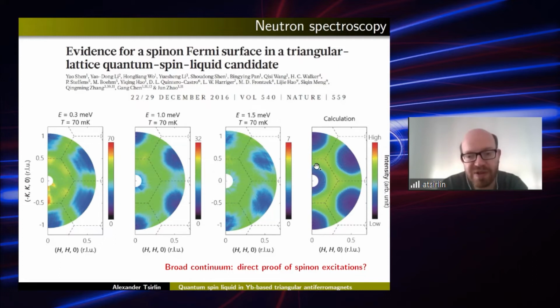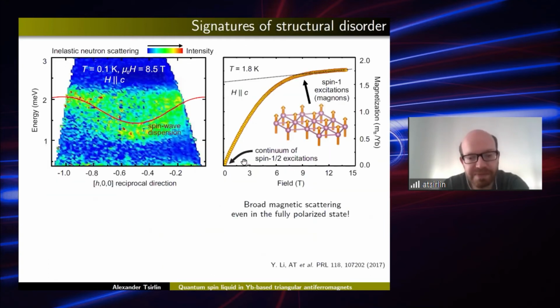And they could even reproduce it quite well using a simple phenomenological model, which made them come up with this claim of spinon Fermi circles in a triangular quantum spin liquid candidate. So that was all fine, and it seemed like the good material is already there. But the problem was that this description was purely phenomenological, so it was not really clear what are the interactions that drive this behavior. And that's what we tried to figure out. So how do you do it? Well, when you have this continuum of spin-1/2 excitations, you cannot really do much with it because it's so broad and sort of uncharacteristic.